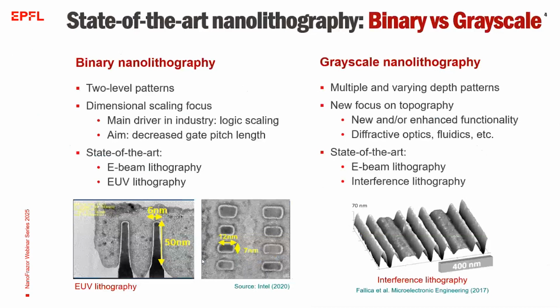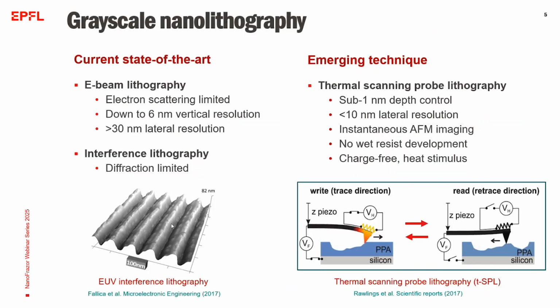When we are talking about nanolithography, traditional nanolithography primarily focuses on downscaling, achieved through techniques like electron beam and extreme UV lithography. In contrast, grayscale nanolithography is based on non-binary shapes with varying depth profiles, enabling novel functionalities in applications like optics and fluidics. Similarly, common techniques for achieving these grayscale patterns are electron beam and interference lithography. However, E-beam lithography is limited by electron scattering, offering resolution in the tens of nanometers, while interference lithography is constrained